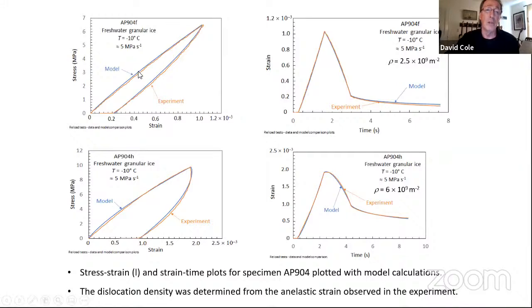The model are the blue lines, and the orange are the experiments. And for these lower levels of damage and lower dislocation densities, I have no complaints over this fit. It actually almost looks a little suspect because it's so good. But I will say again, the only thing I'm doing here is taking all the model parameters and putting in these dislocation densities that we determined to get the anelastic response right. I'll also note, though, that I'm not attempting to model the viscous component. That's going to be pretty complicated, and I just didn't have time to really get into that.